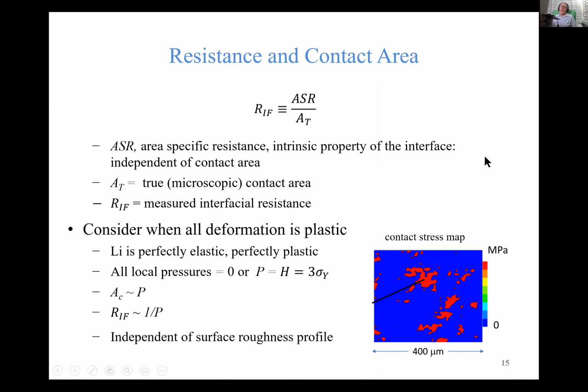So now I want to consider a hypothetical case where you bring a solid electrolyte against lithium metal, and we're going to consider the case where all the deformation is plastic. So here is a representation of that. We have a contact stress map. The color tells you the surface normal stress. And at every point, the local pressure is either zero, blue, which means it's not in contact at all, or it's red, which means it's at the hardness value of 3 times the tensile yield strength. Now, in a case like this, if you double the stack pressure, you have to double the contact area. And that's because since all the contact is at the same pressure, you need double the area in order to support double the load.